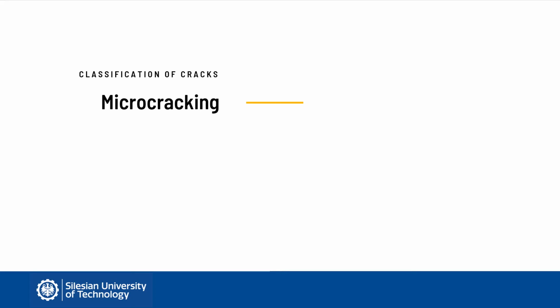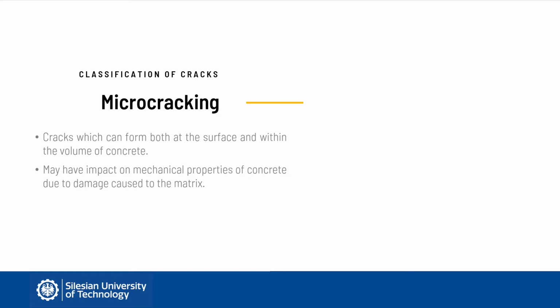Let me say a few more words about microcracking of concrete. As mentioned before, microcracks can form both at the surface and in the volume of the element. Damage to concrete always initiates with formation of numerous microcracks, some of which later concentrate and create large macrocracks when reinforcement becomes involved into transfer of stresses. It can be said that formation of microcracks within the element somewhat contributes to the growth of the pore structure. Therefore, microcracking may have adverse impact on mechanical properties of concrete, such as strength and stiffness, due to the damage of the matrix. It also influences physical properties of concrete, especially those related to its permeability.